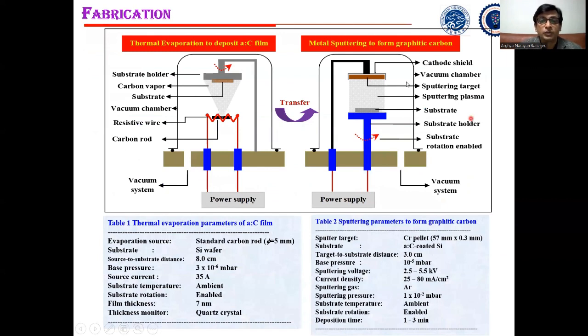Therefore, in our process, we have used a two-step process. In the first step, we used a thermal evaporation technique to deposit a highly thin film, 5 to 7 nanometers thick, of amorphous carbon on a silicon wafer, and then we transferred it to a sputtering chamber to sputter some metal nanoparticles to create this graphitic microporous carbon network.